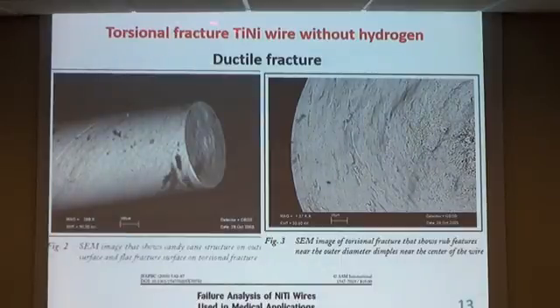Torsional fracture of titanium nickelide wire without hydrogen. Ductile fracture, flat surface, dimples near the center of the wire.